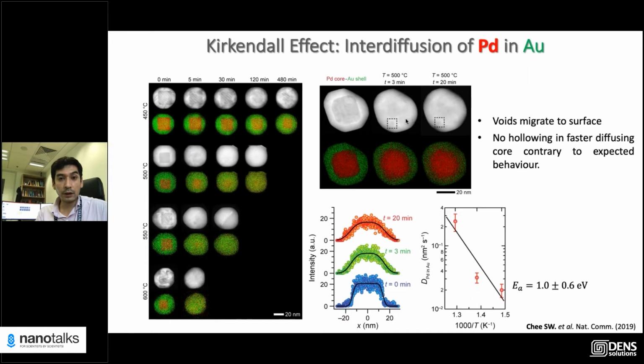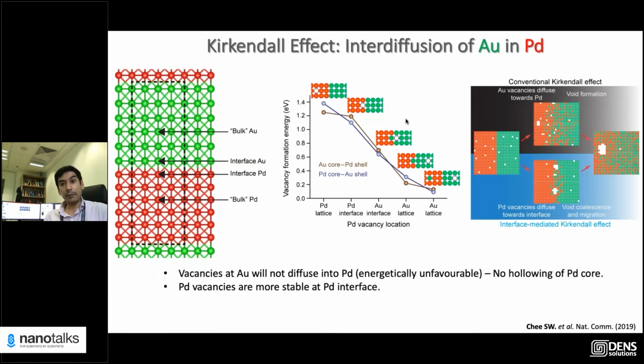You can monitor the structural changes, and this can be explained through DFT simulation. Before I explain, I just want to note this is what you see in a classical Kirkendall effect, right? You have interdiffusion, voids start to nucleate in a material, and the interface kind of diffuses around. But what we see in most cases is the nucleation of the voids happens right at the interface.